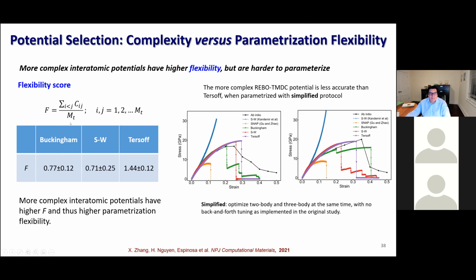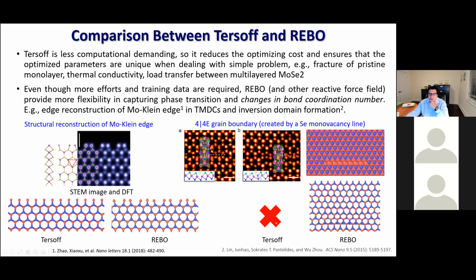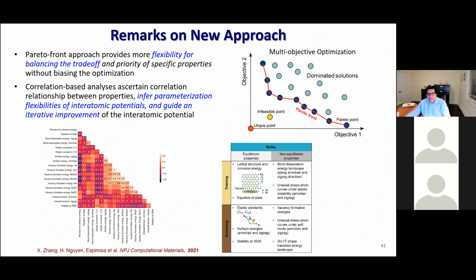REBO is another potential that is more complex. Just to summarize, what we found is that there are certain conditions, like for instance, grain boundaries due to formation of line vacancies, where Tersoff cannot predict a stable structure, but the parameterization of REBO is able to, which shows that in more complex scenarios of grain boundaries and so on, more complex force fields are needed and you can parameterize them.